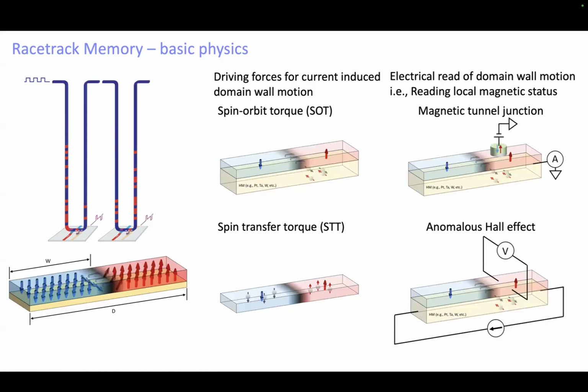And then, how do we read the domain walls? There are different techniques. There are many optical techniques. But electrically, there are two obvious techniques. One is the anomalous Hall effect. The spin Hall effect is a spin polarized current created in a non-magnetic metal. In a magnetic metal, you then see an anomalous Hall effect, where typically the magnitude of this transverse voltage is proportional to the magnetization. That's in conventional ferromagnets. Today, one can see anomalous Hall signals even in systems without any magnetization, in chiral antiferromagnets, for example. And I'm going to briefly come back to that later if there's time.